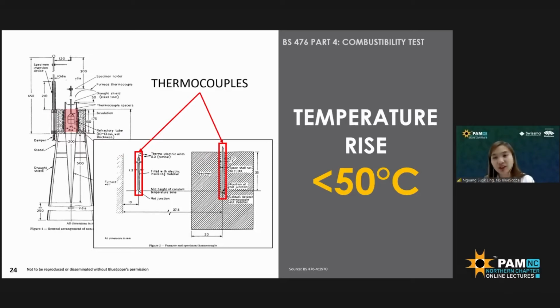So in order for the building materials to be classified as non-combustible, the first criterion is that the measured temperature in the test specimen and adjacent to the specimen should not exceed 50 degrees Celsius from the initial stabilized temperature of 750 degrees Celsius, which also means that the temperature reading measured by the thermocouple shouldn't exceed 800 degrees C.